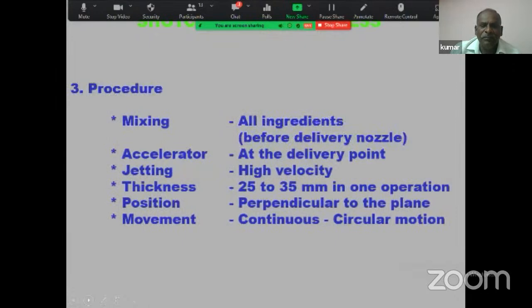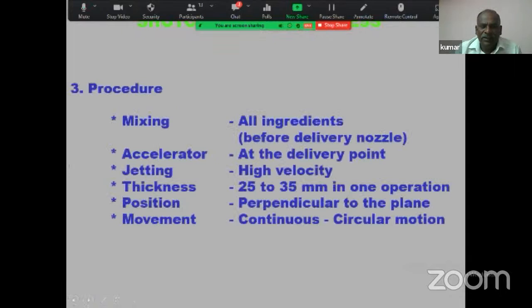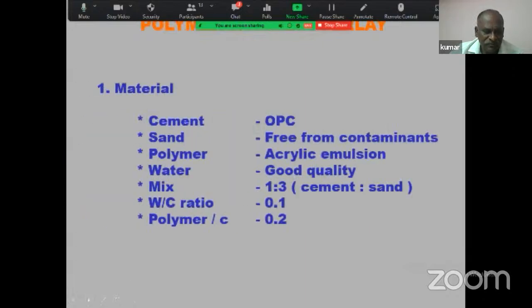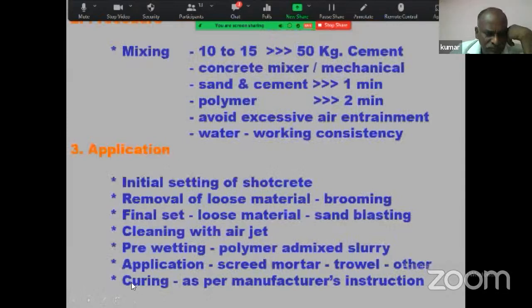So this is the mixing, all ingredients, you have to mix it properly. And the high velocity jetting is to be done. So thickness in one operation is 25 to 35 mm. Perpendicular to the plane, you have to have continuous circular motion. You can apply over there. The shotcrete will build up nearly 25 to 35 mm thickness. So these are the materials.